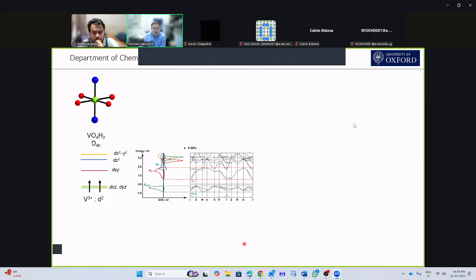What we can do is calculate the DFT band structure of SrVO2H, and that's what I'm showing you here. Then we can integrate this back into a sort of local configuration. What I'm showing you here is the spin polarized density of states. The left-hand side is spin up, the right-hand side is spin down, and we can see this filled band below the Fermi energy corresponds to filling the xz and yz orbitals with 2 electrons. What we see is the Mott-Hubbard kind of interaction here leads to a band gap opening and insulating behavior. But I can apply high pressure to this system and convert it to a metal.